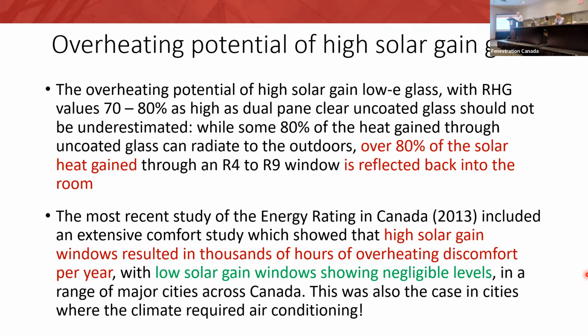But when I studied that chapter, I realized that it showed that high solar gain windows resulted in thousands of hours of overheating discomfort per year in cities across Canada. Some better, some worse than others, but in no case was it less than thousands of hours a year of overheating. And this was in an archetype home with a 15% window to floor ratio and air conditioning in the geographic areas where air conditioning is common. So even with air conditioning, thousands of hours of overheating,